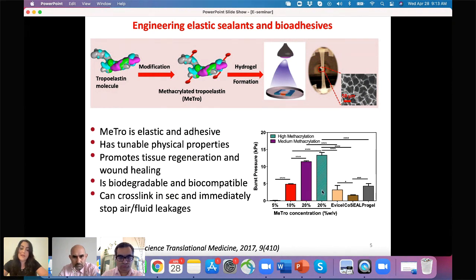About the tunability of MeTro, for example, here are some data based on burst pressure of MeTro when we use it to seal different defects. We show that by changing the polymer concentration or the degree of the functionalization in MeTro, you can tune the burst pressure of this biomaterial. We also compare our data with a different type of surgical sealant. Evicel is a fibrin-based sealant, CoSeal is a PEG-based, and also we use Progel, which is the only FDA-approved sealant for lung application. And we aim to engineer a formulation that has higher burst pressure as compared to commercial product.